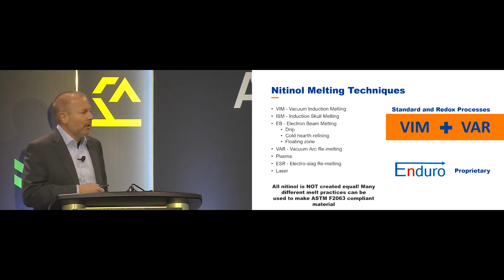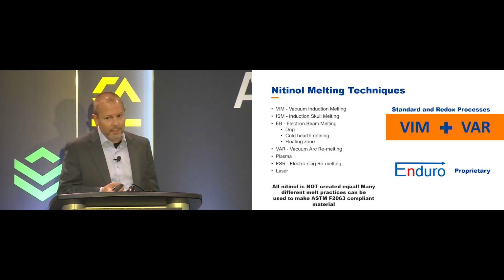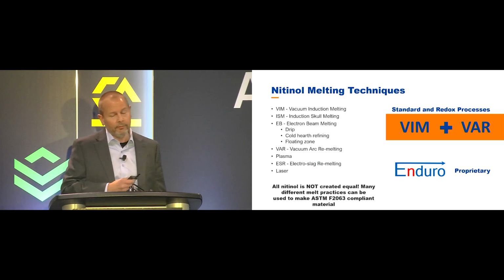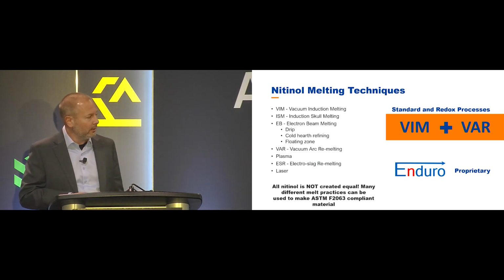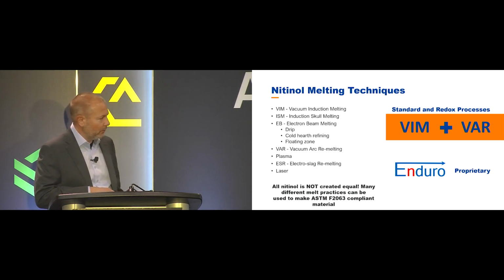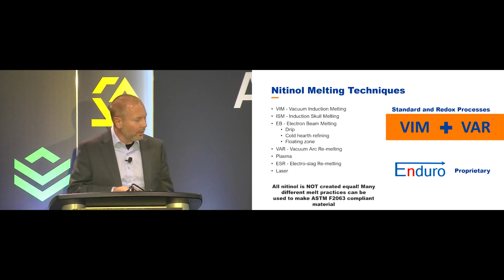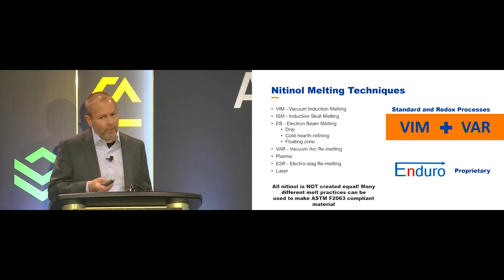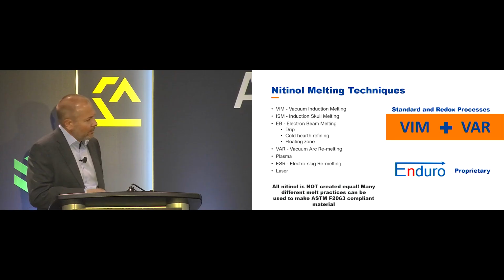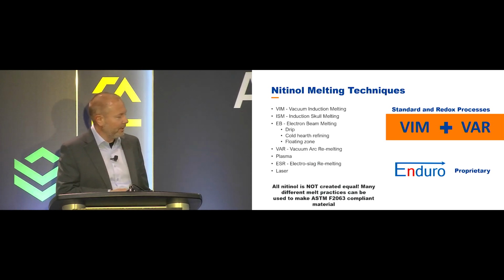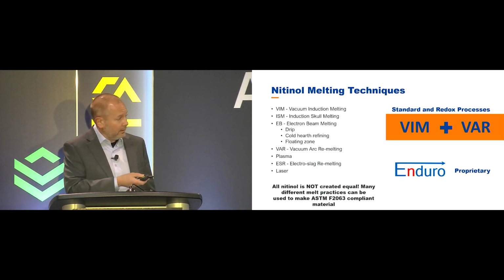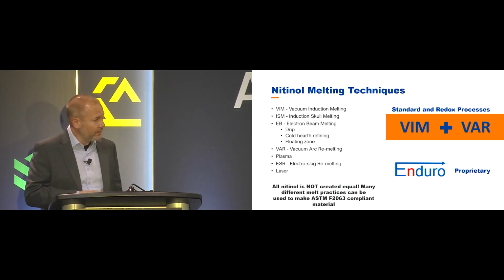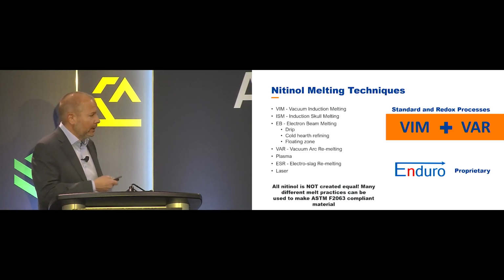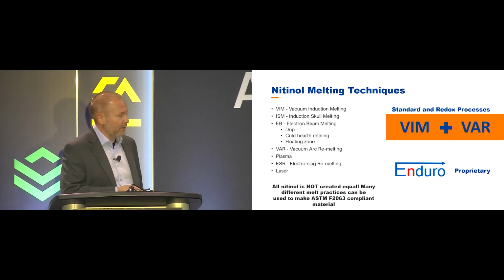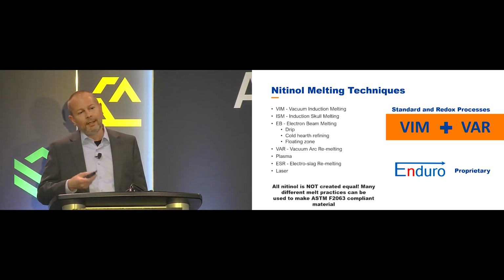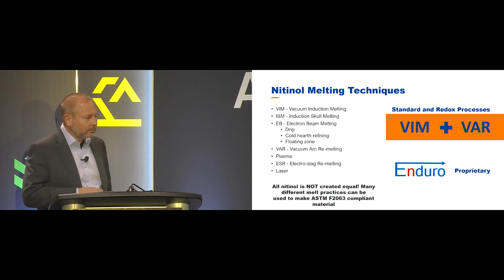For our material, almost everything we make, 95% is VIM-VAR. So we do a vacuum induction melt followed by a vacuum arc remelt. I have some slides that show you what those processes look like. In our Enduro, we're claiming that as proprietary today, so we don't divulge that. But our competitors, other people playing the space, they may use the same technology. We call it the melt practice we do. Some are VAR only, multiple VAR. There's some various practices, and that's one thing that's very unique about nitinol. It's not all made the same.